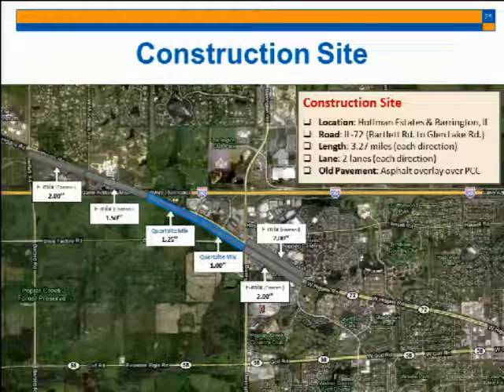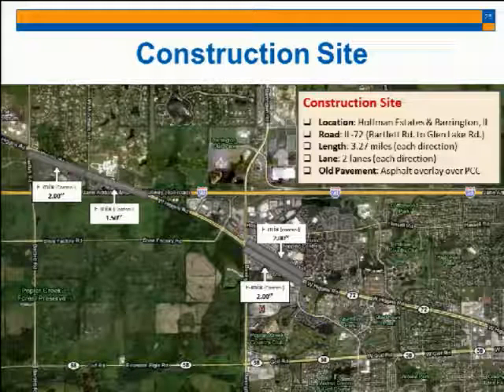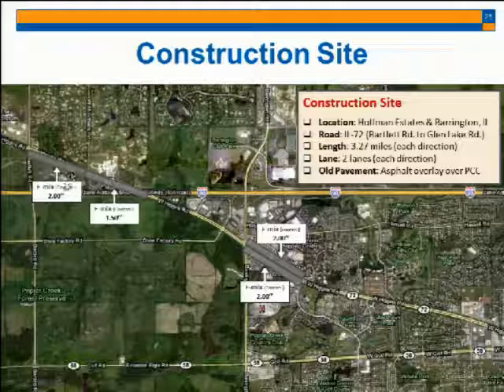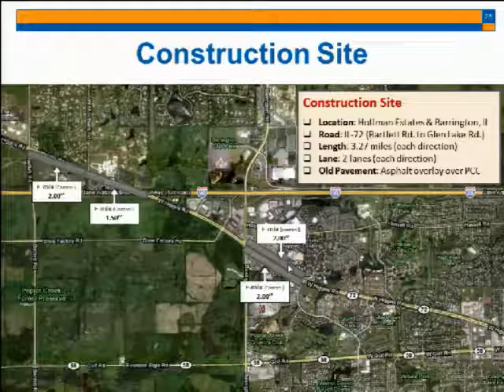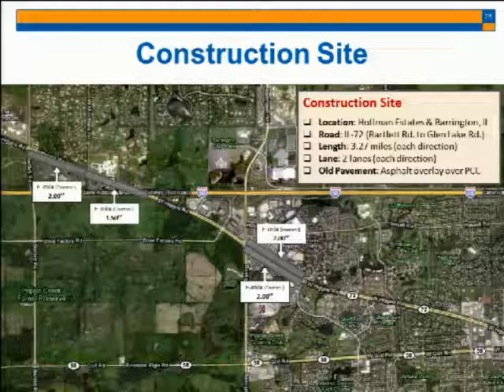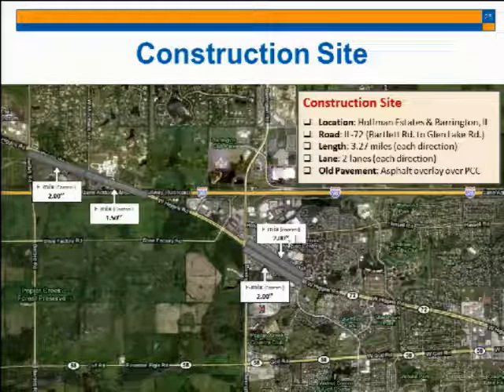We placed these 6 mixtures in the field site, which is close to Schaumburg in Chicago. First, we put the F mix in 4 sections with 2 different thicknesses to see the thickness effect on the performance. But we also put 2 sections here with the same thickness of the same materials to see the traffic effect. Even though we are assuming the same traffic, there might be some difference between the directions. So that's why we put the same materials with the same thickness here at 2 different directions.